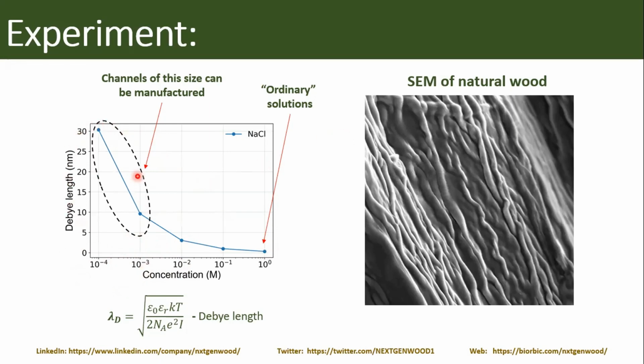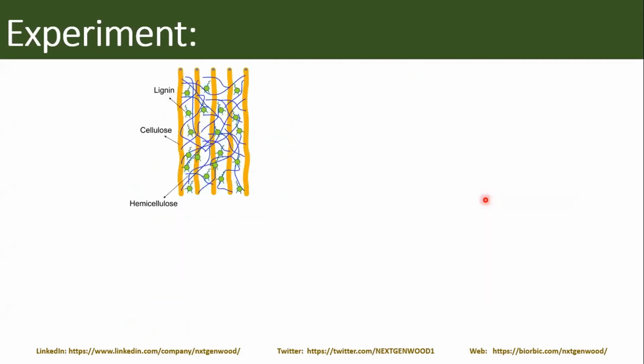And then we found wood, because we know that wood is a quite complicated material where we can have these fibers of cellulose. They are long, very well aligned, and they are of the size which is very promising for us. And if you look at this SEM image at the same time, you see that there are no channels because something is covering these cellulose fibers, and there's lots of other material. And I'm sorry for my very bad drawing skills, but that's what I was trying to explain here. So we have the cellulose fibers, which are shown here as these yellow lines.